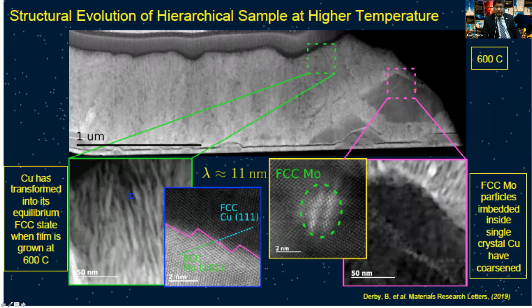It's more of a linear array. So you can see those white lines. Those are actually dots of moly precipitates that have lined up along certain directions inside that island. So clearly there is structure forming inside structure. There is first a kind of phase separation, then there is phase separation inside that, and there is a different kind of phase separation inside the other domain. So a very bizarre and interesting kind of morphology that is forming during deposition.